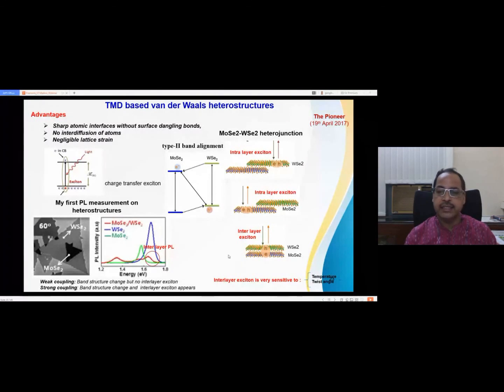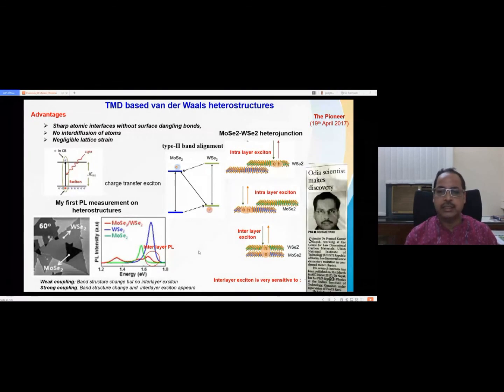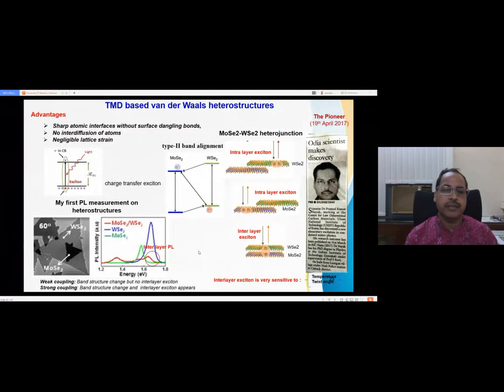Okay, and this interlayer exciton is very sensitive to the twist angle and also the temperature, because when you go down in temperature, all the phonon vibrations cease, and the intensity of the interlayer exciton will be very, very large. But we have done the room temperature measurement only. I will show you in the next slide how it is. And this is the first media coverage of our interlayer exciton. Okay, so this was published in ACS Nano in 2017.